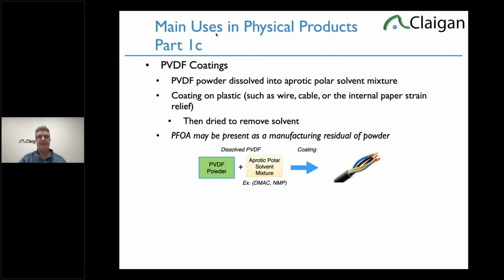So when they bend, they don't bind, and the flexible cable lasts a lot longer. And that's a PVDF coating. It can have PFOA from the original PVDF manufacturing. We often really see a sulfonated fluorotelomer called 6,2-fluorotelomer, more often than we see PFOA in this situation, which is not regulated at this point in time outside of carpets. But the PFOA that's in there, or the 6,2-fluorotelomer sulfonate, are unintentional, not reportable.